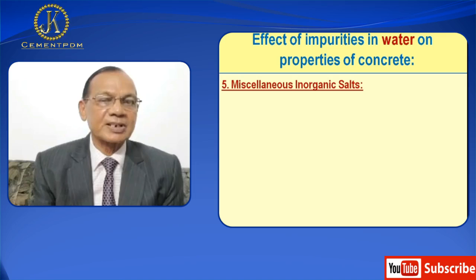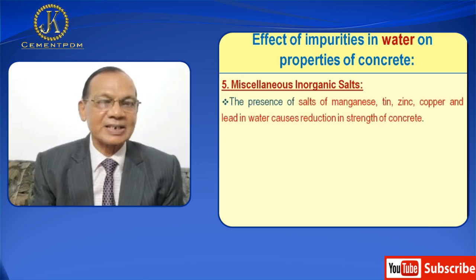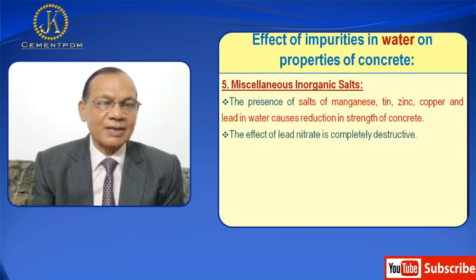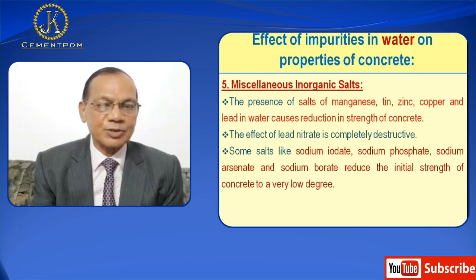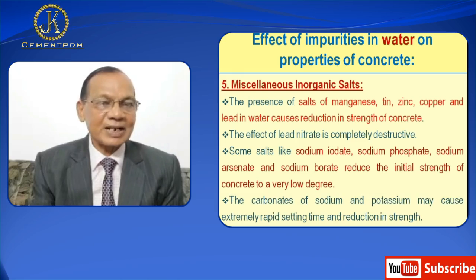Number five, miscellaneous inorganic salt. The presence of salt of manganese, tin, zinc, copper, and lead in water causes reduction in the strength of concrete. The effect of lead nitrate is completely destructive. Some salts like sodium iodate, sodium phosphate, sodium arsenate, and sodium borate reduce the initial strength of concrete to a very low degree. The carbonates of sodium and potassium may cause extremely rapid setting time and reduction in strength.